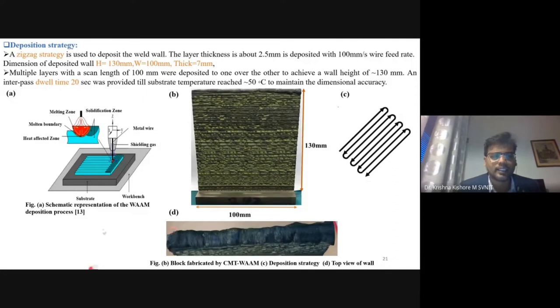If you can see here, this is an entire deposition. The width of this deposition is like 3 to 4 mm, and we have achieved this 3 to 4 mm like this. This deposition did not happen in a single pass, it happened in this weaving bead. So we used a zigzag strategy to deposit. To achieve this much width, we gave the path planning for the torch movement in this direction, right? So it goes in this zigzag pattern, depositing the molten metal.